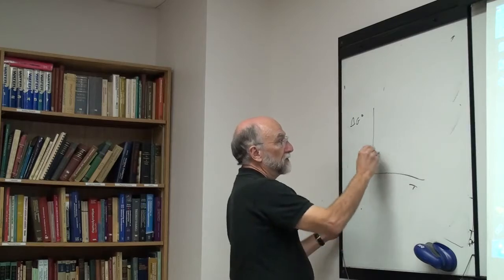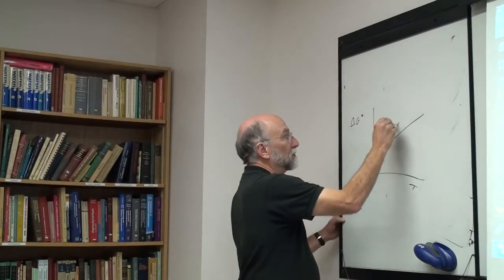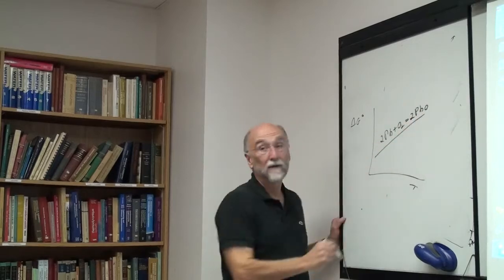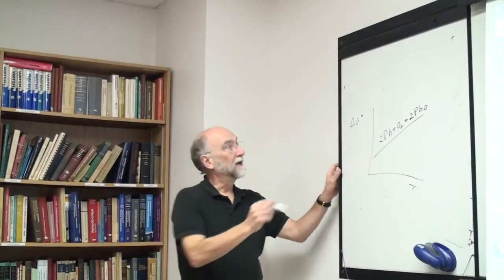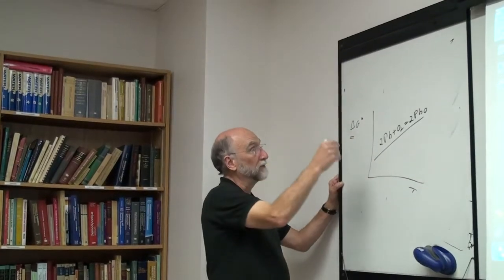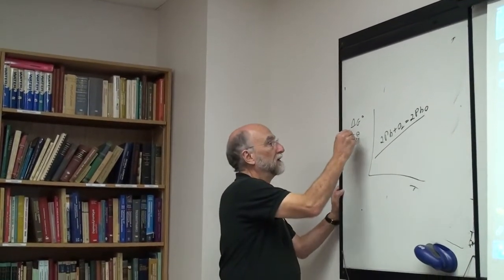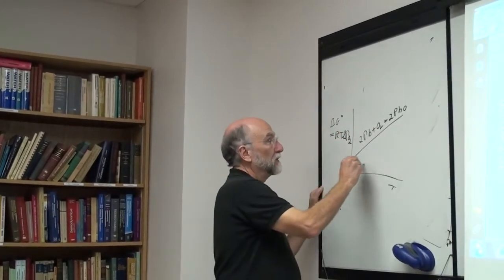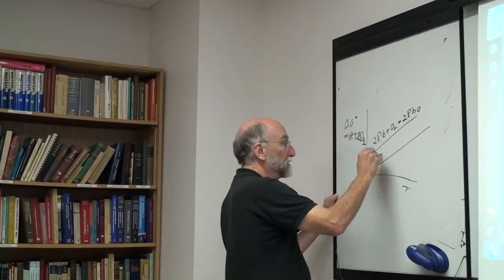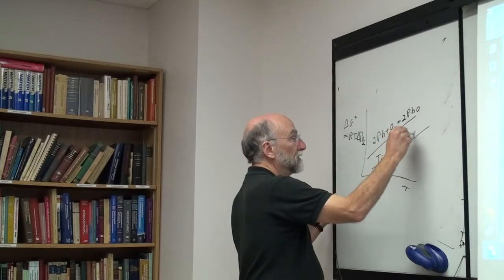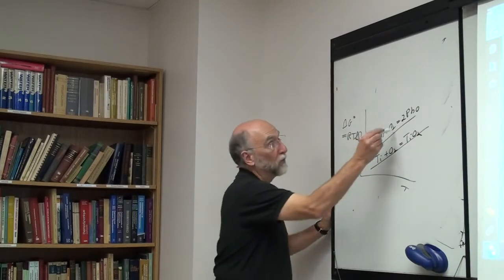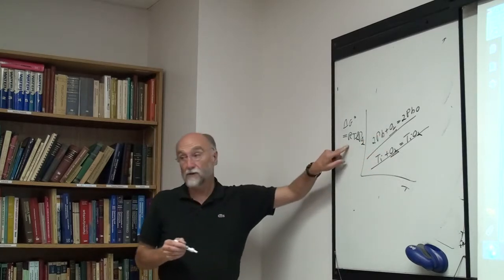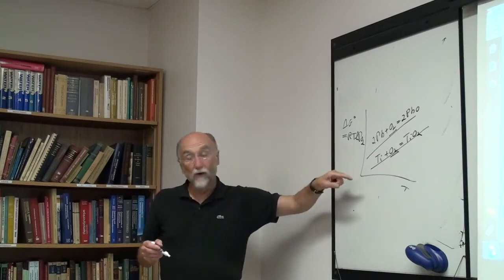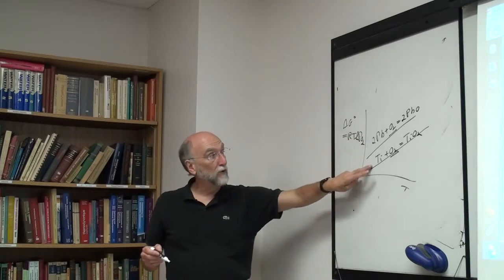This is so you can compare things. So if you plot an Ellingham diagram, you'd have delta G0 versus temperature. So if here you had, say, 2 Pb plus oxygen equals 2 PbO, that gives the energy for that reaction. And the delta G0 then is minus RT log 1 over PO2, or RT log PO2. If you were to plot, say, titanium, it would be Ti plus O2 equals TiO2. Always 1 mole of oxygen. So this is always RT log PO2. And why is it 1 mole of oxygen? So you could compare them. Titanium is more reactive than lead.